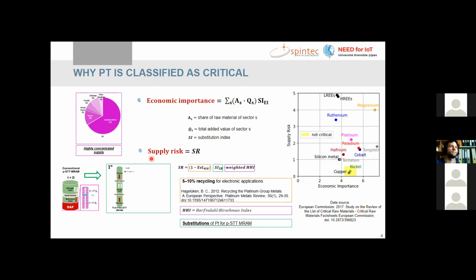One will be based on perpendicular shape anisotropy, and the second one based on building cobalt-nickel multilayers. So I will go for this cobalt-nickel multilayer alternative. So why nickel? Because as you see here in the matrix, nickel is classified as a non-critical material and has a much lower supply risk. Also it has a much smaller environmental impact. So this is another advantage as well.